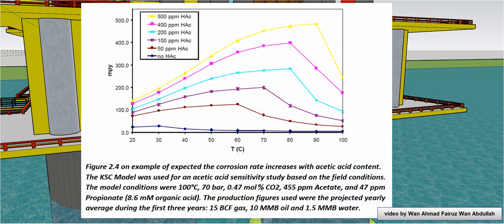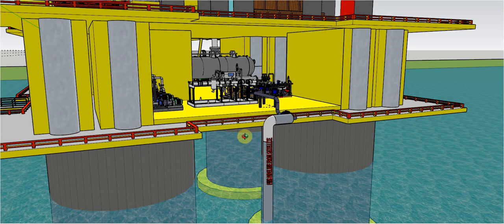Then we can see the trending example of the expected corrosion rate increasing with the acetic acid content. This is the KSC corrosion modeling that was used for the acetic acid sensitivity study based on the field condition. The model condition was 100 degrees Celsius at 70 bar, and we found the corrosion rate is greatly and proportionally increased with the content of the organic acid. There are several other trends that I put in the submission paper, and we can explain further during the mocking session.